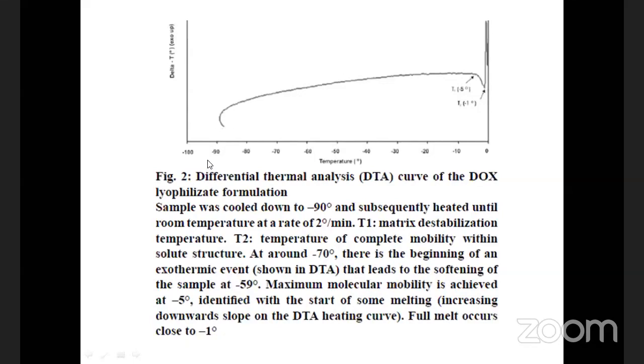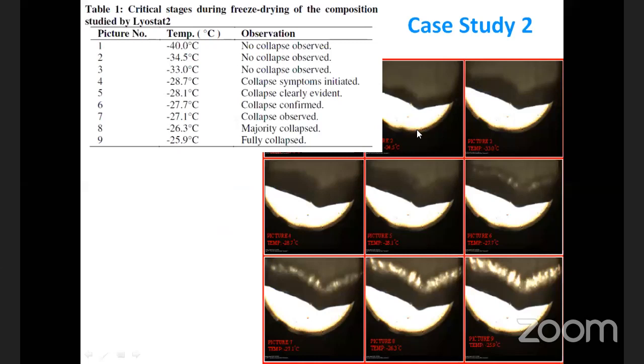So these results we can compare with DTA, the integrated version of this equipment. The same temperatures you will find here, at -5 degrees Celsius at this one. There is a decline in the energy curve and a complete melting at this -1 degree Celsius. This is another example of critical or collapse temperature determination.